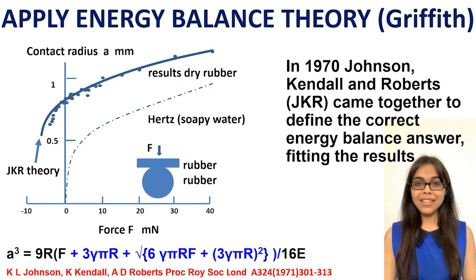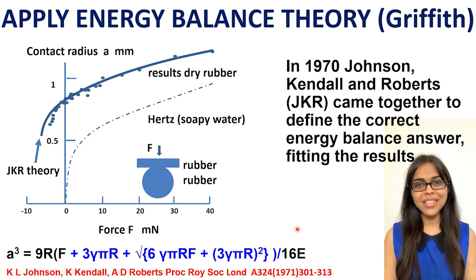It was 1970, 12 years later, when Kendall realized that it was necessary to apply Griffith's energy balance. Many stress experts still think that stress causes failure. No, it is the conservation of energy that prevails. The energy balance worked out by Ken Johnson on Cup Final afternoon in 1970 showed that the Hertz equation needed 3 more terms to fit the results, as shown in this equation and this graph.